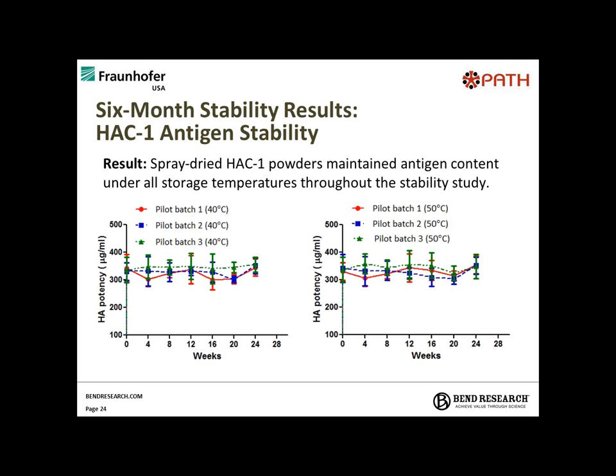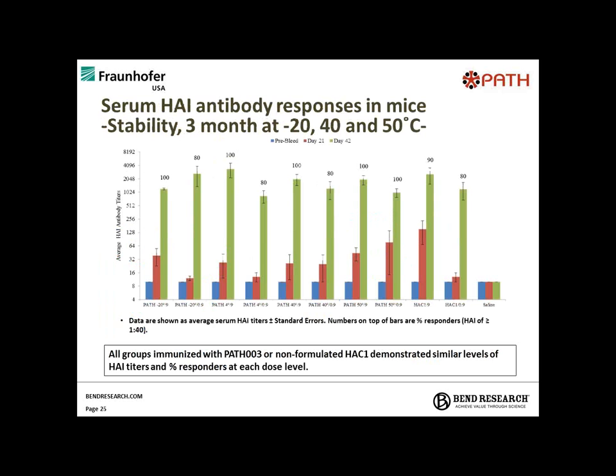Our collaborators, PATH and Fraunhofer, did some in vitro analysis looking at potency across 6 months at 50 degrees Celsius and 40 degrees Celsius of this HAC1 antigen, and saw that in this formulation at these conditions, the potency was maintained and held strong, which was great from an in vitro standpoint. But obviously to prove this in vivo, Fraunhofer also analyzed the stability study powders using an in vivo challenge, and looked at antibody titer as a function of inoculation dose after the powders were stored at -20, 4, 40 or 50 degrees Celsius. And as we can see, compared to the control, the HAC1 on the far right, our formulated powders maintain the potency as the controls show across a 6-month as well as 3-month stability study.